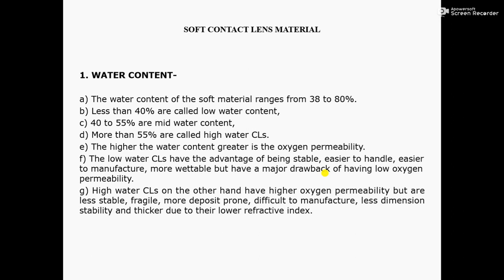High water contact lenses, on the other hand, have higher oxygen permeability but are less stable, fragile, more deposit prone, difficult to manufacture, have less dimensional stability, and are thicker due to their lower refractive index.